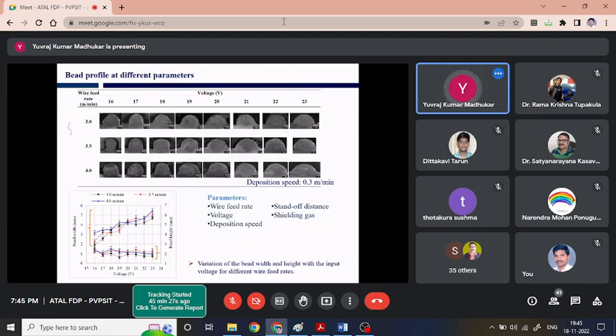So here we could see, for different voltages starting from 16 volt to 23 volt and different wire feed rates, the different bead properties that can be found. Here we could see the bead width increases almost linearly with respect to the voltage. However, the bead height remains almost constant. Yes, it is quite obvious, since we are increasing the voltage, that means we are increasing the input energy. It is quite obvious, but we have to optimize it.